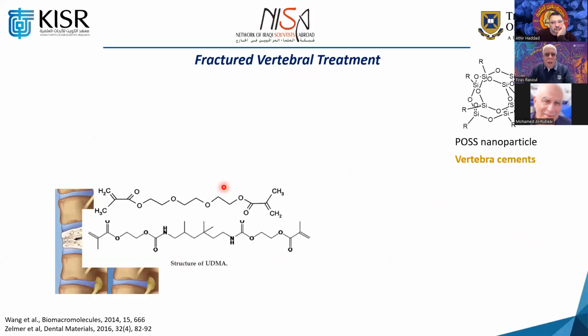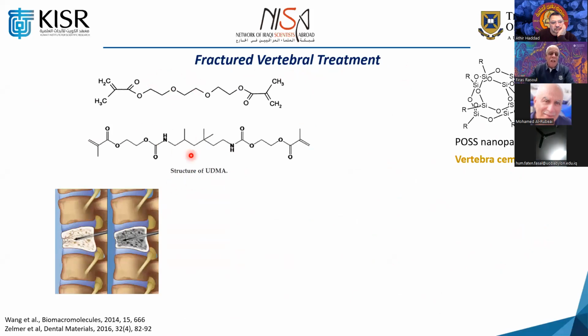for that. We used it in combination with two monomers. These two monomers are typically used for a variety of applications, and one of them is for dental fillings. But we combined it with our nicely developed one, this POSS. And we expected that by combining this, first of all, because they are macromolecules, when they polymerize, they don't produce high temperature. So the exotherm temperature is going to be much, much lower than using a different type of small molecule monomers like methyl methacrylate and others. So this is one of the expectations.